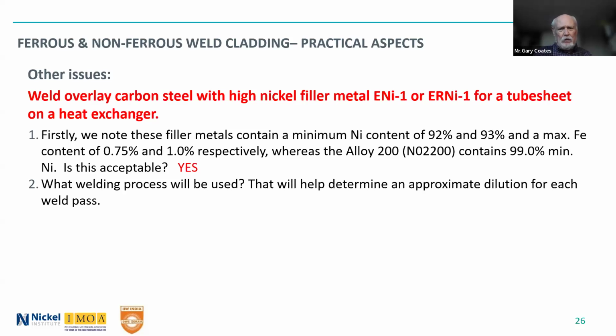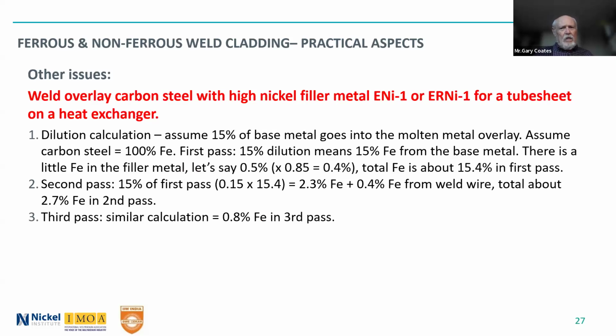What welding process will be used? That will determine an appropriate dilution for each weld pass. So if we assume 15% dilution of base metal into the weld overlay, and we'll again assume the carbon steel is 100% iron. The first pass, 15% dilution means 15% iron from the base metal goes into the weld overlay, but there's also a little iron in the filler metal, a small amount, 0.4%. So you have 15.4% in the first pass. That would be generally considered unacceptable. In the second pass, you have 15% of the first pass in there, and then the little bit from the weld wire, and you have 2.7% iron. So perhaps you can get away with that, and we'll come back to that shortly.